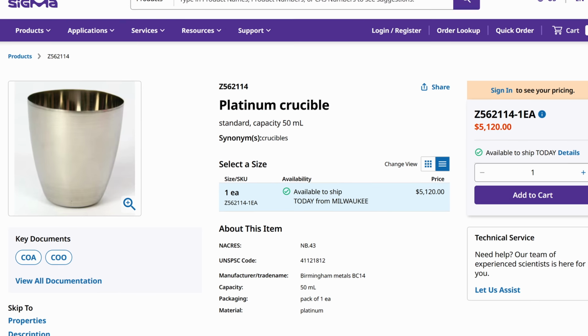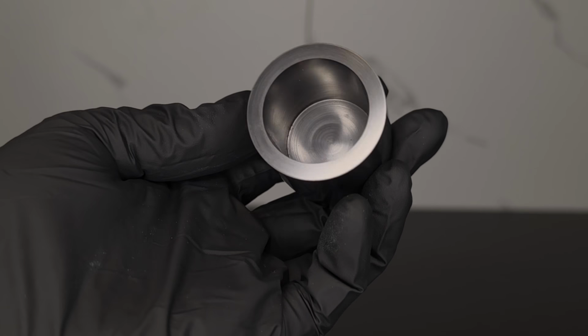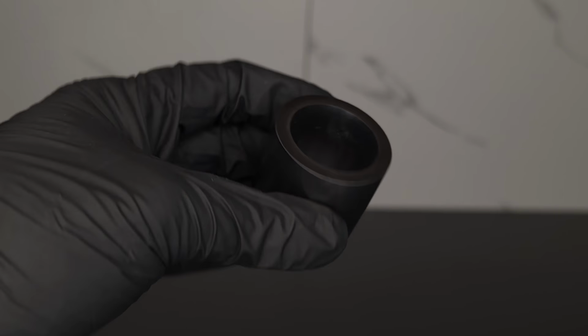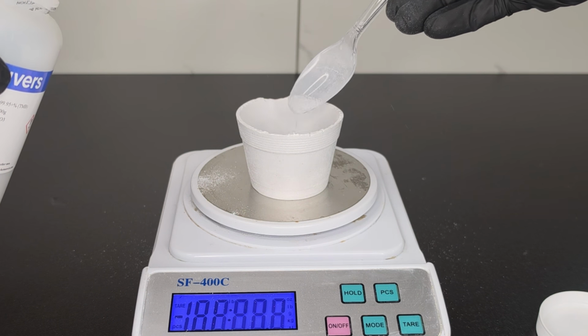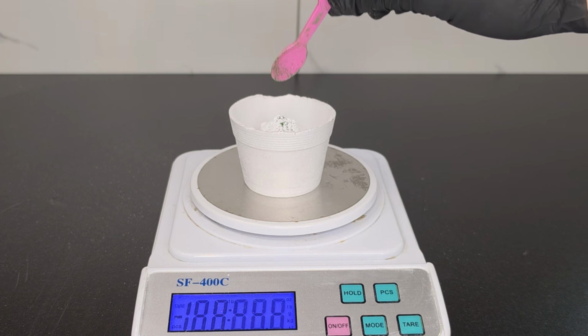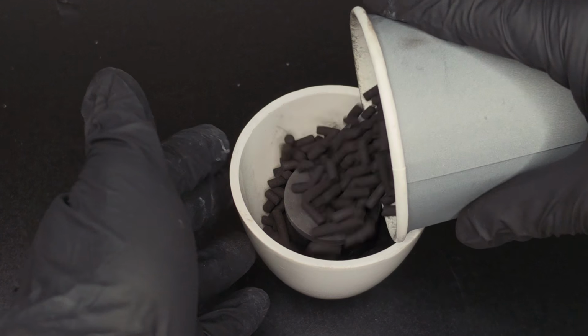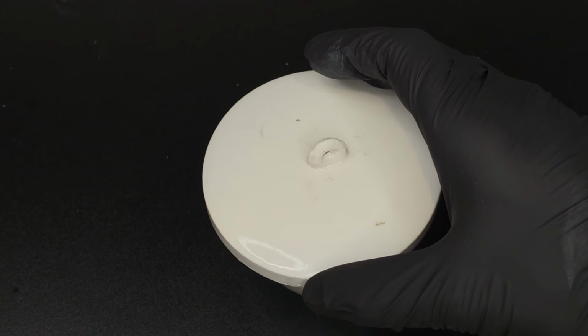The platinum crucible was another problem. They're very expensive and I didn't have one. What I did have was a graphite crucible, which is cheap and non-reactive as long as you keep oxygen away from it. So I just took some molybdenum oxide, some chromium oxide, and some aluminum oxide, mixed them together, and pressed them in. I packed the whole thing in charcoal to scavenge oxygen and set it to cooking.